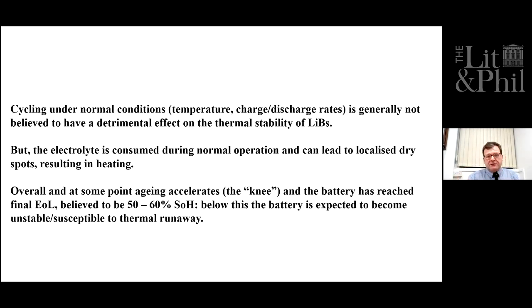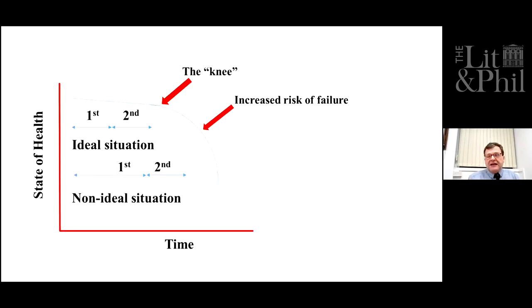So what about the aging and the abuse of batteries? If you cycle batteries, in other words charge and discharge, within their set limits, there's no problem at all. Electrolyte is consumed because we get loss of the lithium during the lifetime, and that can lead to dry spots, local dry areas. But overall, it's perceived that if you do what you're supposed to do, there shouldn't be a problem. But at some point, the aging of the battery will accelerate, either due to new aging mechanisms or simply due to the acceleration of the existing ones. And once the battery passes about 50% to 60% state of health, in other words has about 50 to 60% of the original capacity left, then it is perceived that the battery will become unstable and unusable and potentially dangerous. The ideal situation is that the knee occurs after second life, but there is the possibility of the knee occurring during second life.